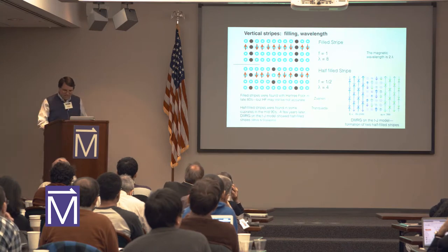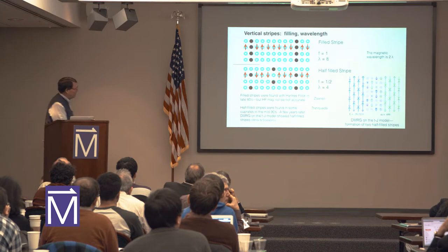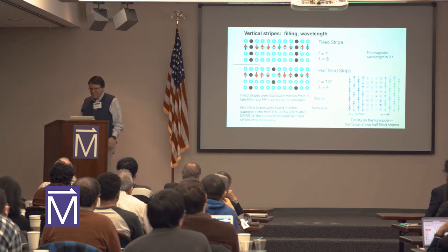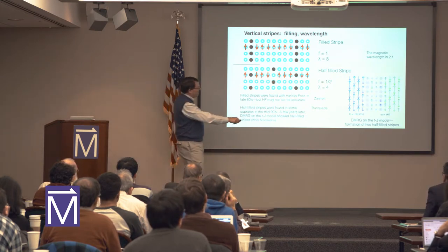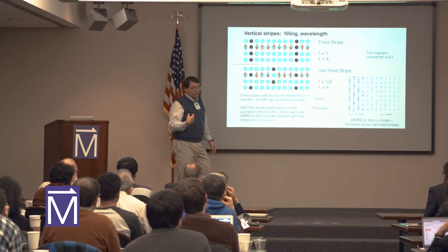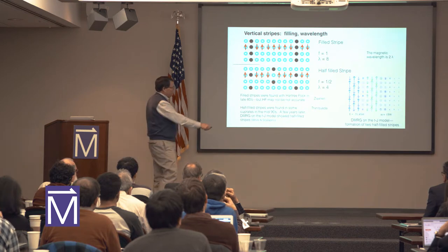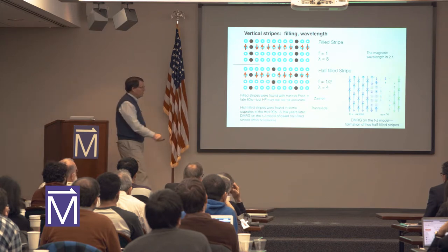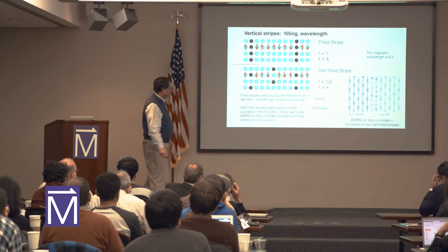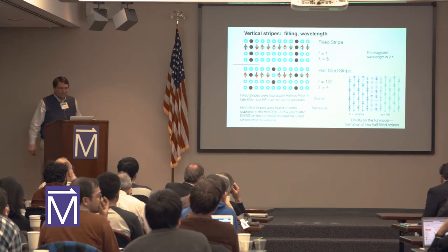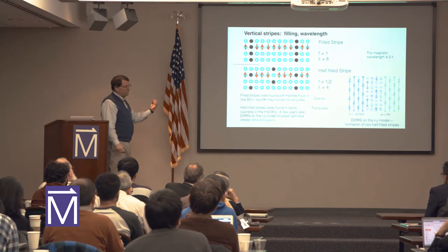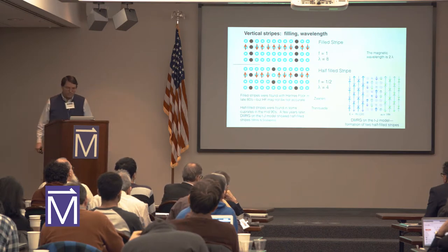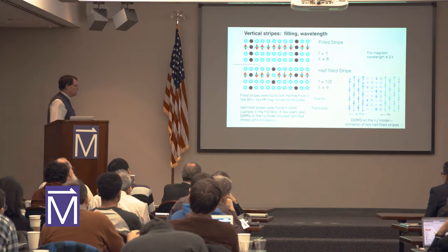We had seen these stripe states in the t-J model — this is work done with Doug over a number of years. In that time we made movies showing how the stripe states arose in the DMRG calculations. These were all in the t-J model, which was easier to do, and you can see in the movies that the stripes just spontaneously form. The stripes we saw in the t-J model were almost always half-filled stripes at this doping. Filled stripes had been found with Hartree-Fock — that was the first thing found theoretically — though those calculations are not necessarily very reliable.